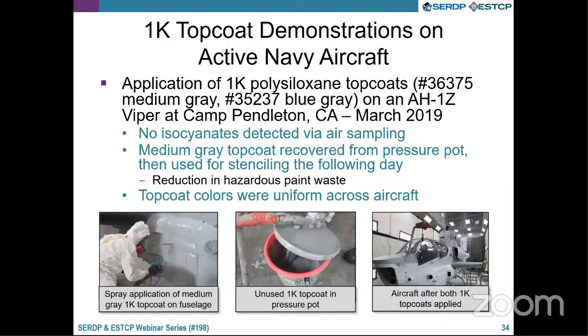The second thing we wanted to show was that because it's a single component material, we can recover unused material. The photo in the center shows a 2-gallon pressure pot; two of these were used, one on each side of the aircraft. About half to three-quarters of a gallon was unused, so we took that material out of the hopper, poured it back into the cans, sealed them, and the following day the medium gray color was used for stenciling over the blue gray single component polysiloxane. Aside from flushing the lines, we had near zero paint waste using this technology.